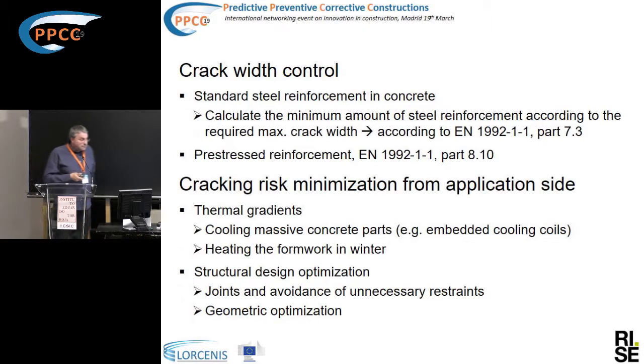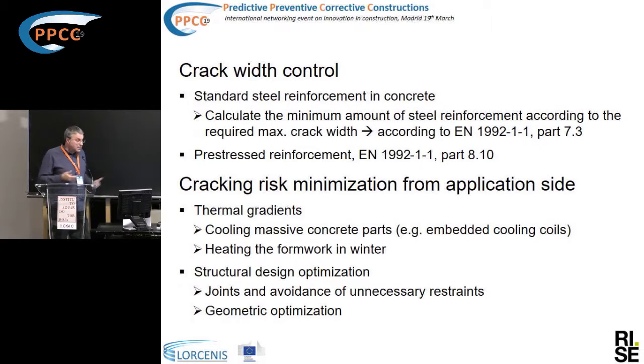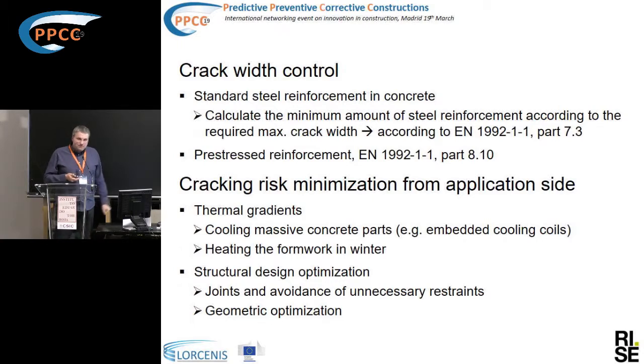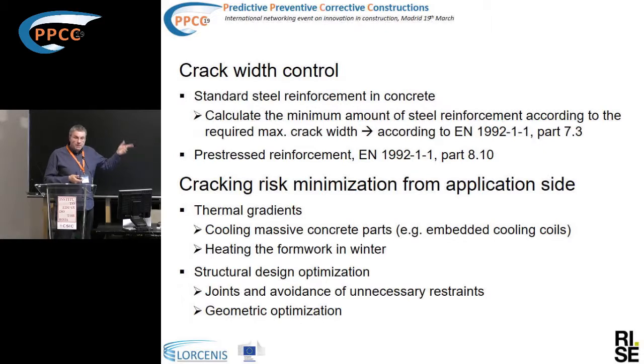For crack risk minimization from the application side — what can be done when concrete is placed to minimize crack risks — for thermal gradients there is an established method of cooling the concrete, either externally or internally using cooling coils. There is a well-known example from the Hoover Dam, where they put in kilometers of copper coils into the concrete to cool it down during hydration.